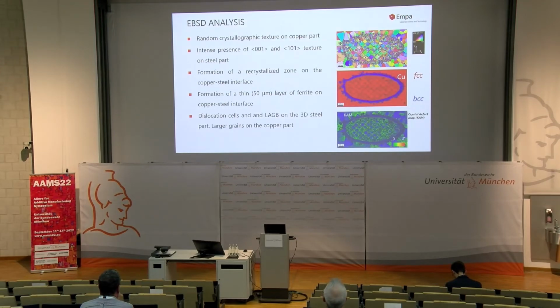Now, by having a look from the EBSD analysis, as we can see here, it is obvious the result of the scanning strategy that we have used for 316L stainless steel. So you can see this rectangular structure. We print unidirectionally, and then we rotate by 90 degrees. So this is the reason for creating these patterns. Actually, the width of these patterns are equal to 100 micrometers, which is the hatch distance that we have used. And we can see the appearance of the 001 texture in the middle of the scanning tracks, and also we have the appearance of the 101 texture. We also see that this interdiffusion zone has been recrystallized, and as expected based on the casting conditions, the copper part has bigger grains and a more random texture.